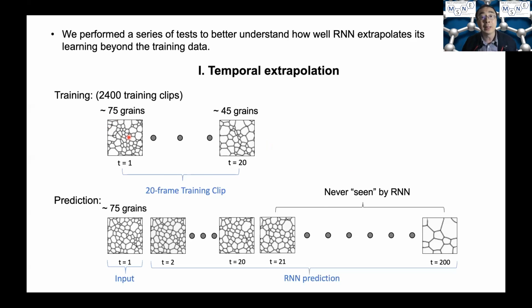So here in generating training data sets, we start from a polycrystal structure that has about 75 grains, and then we let it evolve and end the simulation at about 45 grains. So about 30 grains disappear from the simulation. This is a pretty short simulation sequence. Then we convert each simulation into a 20 frame clip, and we have a total of 2,400 training clips in the training data sets.